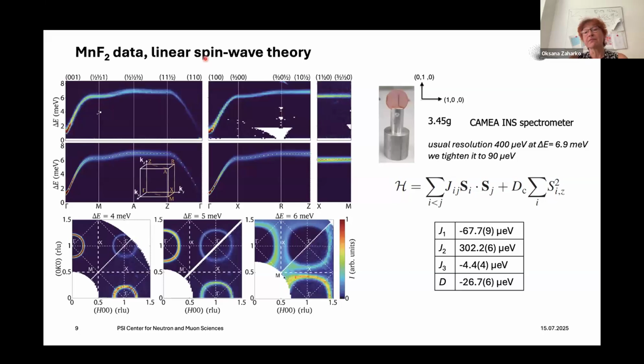Nothing happened on top, but we just had a normal behavior due to the magnetic field, so the Zeeman splitting. If I can make a small remark, I think because of symmetry in this system, DM interaction is not allowed. There are other rutile materials where the spin is not along Z, and there you can have a DM, but not in this particular one. Exactly, not in this type of magnetic order. But in the dynamics, it must appear.